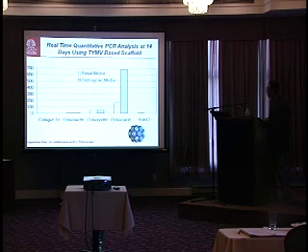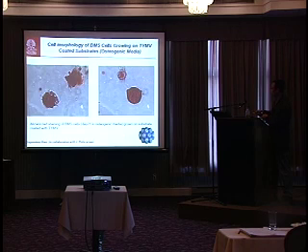And you want to show this kind of shape. What we see here is that at day 14, with our TMV, tobacco mosaic virus-based scaffold, we can already finish the differentiation. With normal tissue culture, or hydrogels from commercial sources, it takes 21 to 28 days. So this nanofiber can upregulate the differentiation of the cells. Also very important, we can control that. This is something I want to show here.